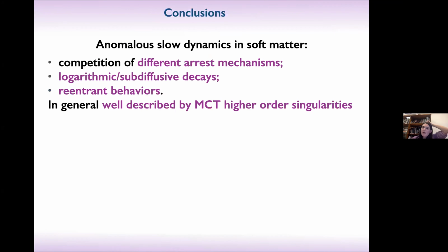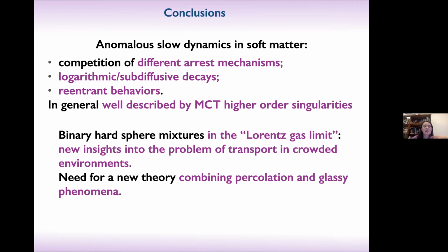So with this, I conclude. I hope I tried to give you my best possible illustration of what I mean by anomalous dynamics in soft matter. You have it when you have competition between different arrest mechanisms. You find this logarithmic subdiffusive decay, sometimes reentrant behavior, and in general, it is well described by MCT higher order singularities. And I showed you also this more recent case, in which we worked with the Lorentz gas limit, in which we get new insights due to this mobility of the matrix that gives also anomalous dynamics, but kind of different from what was known before, which calls for the need of a new theory which combines percolation and glassy aspects.